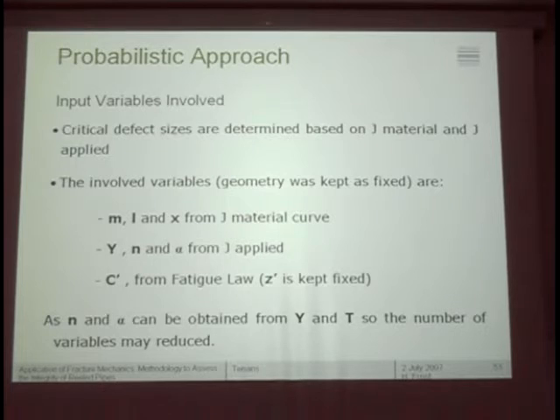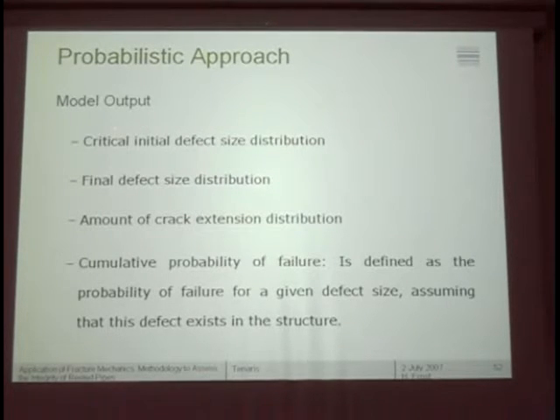Okay? The plant gives you pairs of Y and T, that's what they usually have, and they have not run for each case the complete load stress strain curve. So with all that, the output of the model should be critical initial defect size distribution, final defect size distribution, amount of crack extension, and if you want the cumulative probability of failure, which is defined as the probability of failure of a given defect size, assuming that this defect is there. Okay, I said if I have a defect so big, I'd like to know what is the probability, due to the variability of the parameters, that this defect failed.